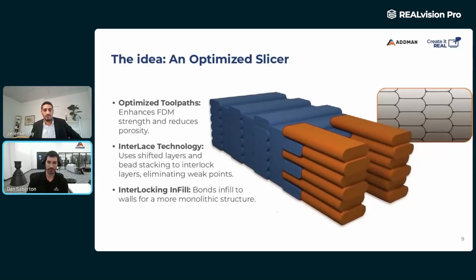There are two main features in the software that we use to increase the strength of the parts. The first one is the Interlace technology, where we use shifted layers to stack the beads in such a way that whenever the part fractures, the force isn't distributed through a straight line through that XY plane. It has to travel and bend all over the place, which increases the strength of the part. Not only that, by stacking the beads the way we do, we're greatly reducing the amount of porosity in these parts, which of course also increases their strength.